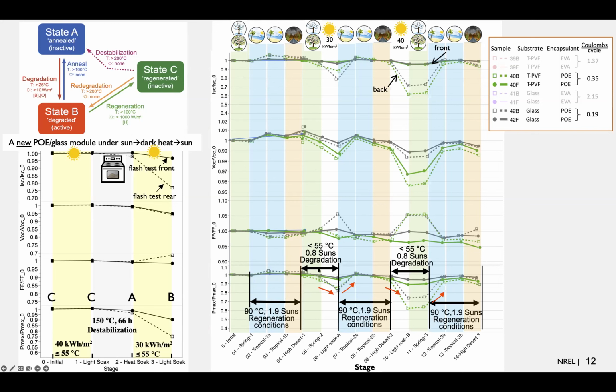But here the lights are on. The issue is that when we went to this spring sequence here, we saw a little bit of degradation, especially when measured from the rear, up to about 5% degradation in ISC, for example, roughly speaking. So we were scratching our heads about this, and for additional diagnostics, we put it under natural sunlight, and we saw yet further degradation.